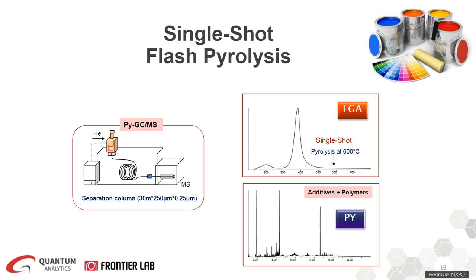Terry, may I add one thing? Of course. One thing that we found is that once you finish using the instrument, if you put the instrument in standby, so reduce the furnace temperature down to a couple of 100 degrees, same with the interface, and same with the GC inlet, the septum on the inlet, the O-ring on the inlet, and the O-ring on the furnace tube last much, much longer in between cleanings and maintenance. Absolutely. Excellent, excellent practice.